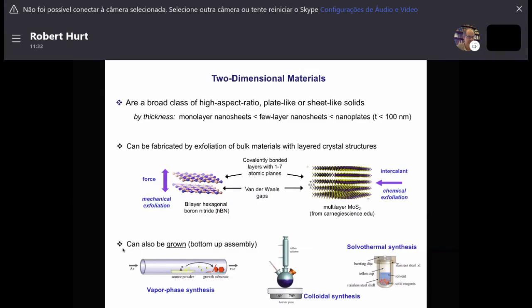The general classes of methods to make these materials are chemical and mechanical. In the mechanical method, force is used, whether it's sonication, intense stirring, or the Scotch tape method, to rip apart layered materials into individual nanosheets. In chemical methods, you intercalate some agent in between the layers to pre-expand the material, and then typically by heating or by solvent contact, decompose the intercalant, creating internal pressure that blows apart and separates the layers of a layered material into 2D pieces. 2D materials can also be grown by chemical vapor deposition, the way we often grow carbon nanotubes, a bottom-up atomic-scale growth process, or they can be grown colloidally or solvothermally. It's quite a large field.